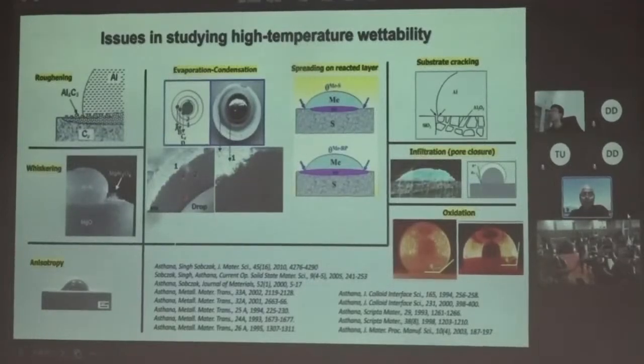So unlike low temperature systems where there is hardly any reaction other than absorption on the surface, high temperature systems show very complex phenomena. So here are some examples that we have been looking at. Aluminum on carbon. You form aluminum carbide by exothermic reaction, and the carbide crystals actually are ahead of the liquid. So the liquid is actually spreading on a modified surface. In other systems, like on magnesium oxide, when you have nickel aluminum, there is reaction and whisker formation.